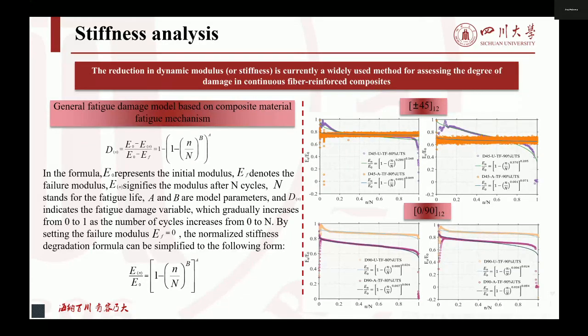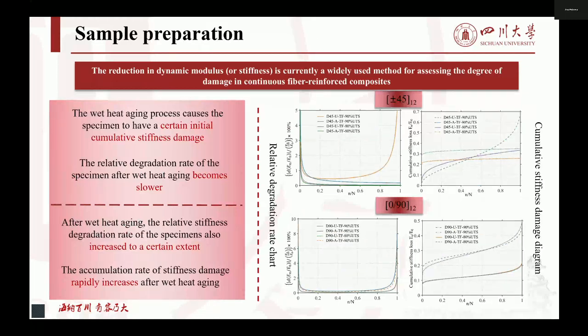The reduction of dynamic modulus or stiffness is currently a widely used method for assessing the degree of damage in continuous fiber reinforced composites. In this study, a general fatigue damage model based on the fatigue mechanism of composites was employed for stiffness prediction. As shown in the right figure, they are respectively the relative degradation rate chart and the cumulative stiffness damage chart.